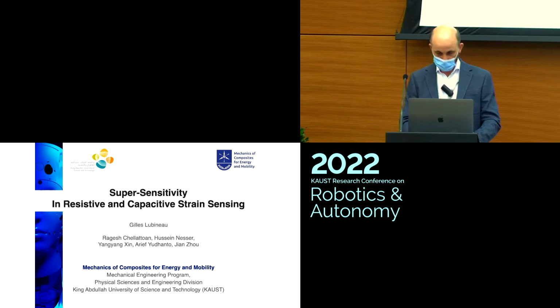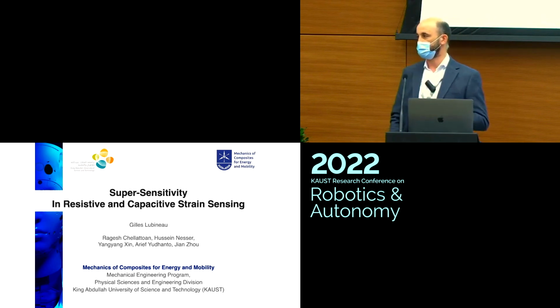What is important is that you get an electrode with a relatively low resistance at the beginning, because if your resistance at the beginning is big enough, you are not going to activate this frequency dependent behavior. So the CNT papers are good for this. But what is also important is that it will keep a conductivity even if you introduce a lot of damage mechanisms. In most systems in which we introduce cracks, for example metallic films, as soon as you introduce a crack you get a high increase in resistance.